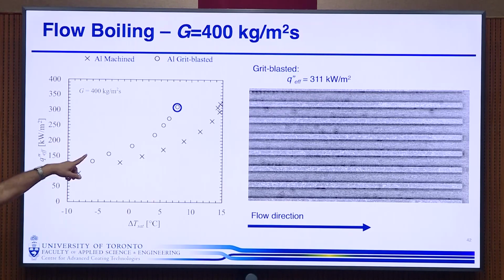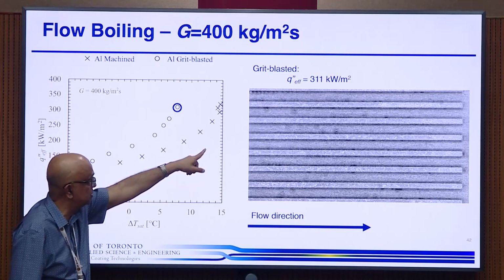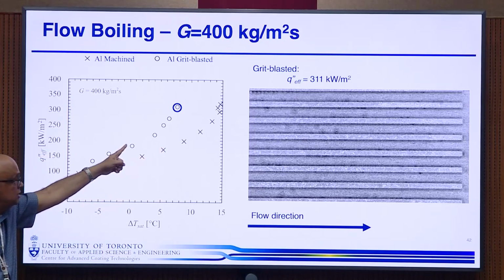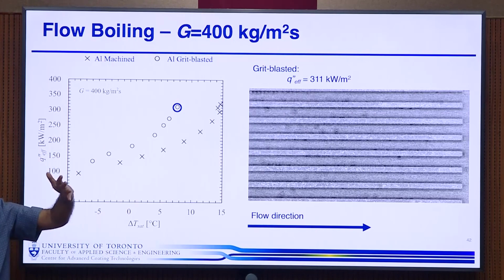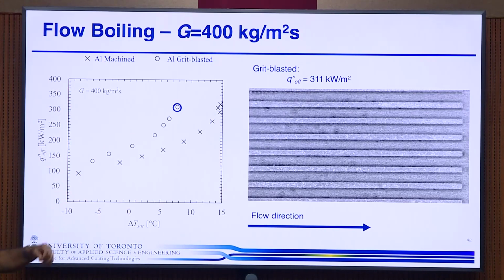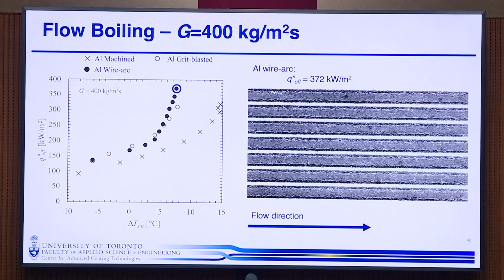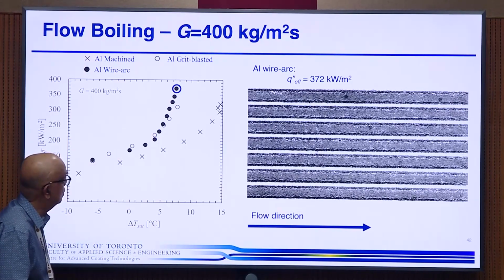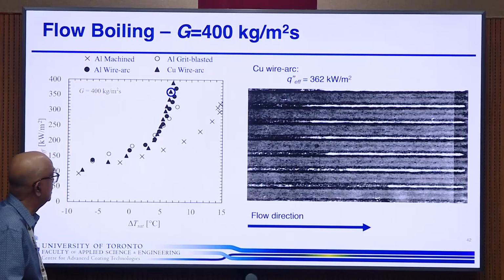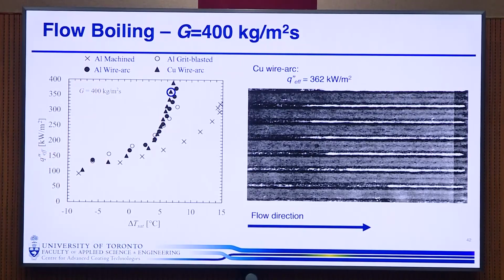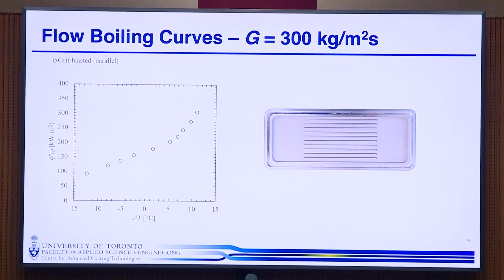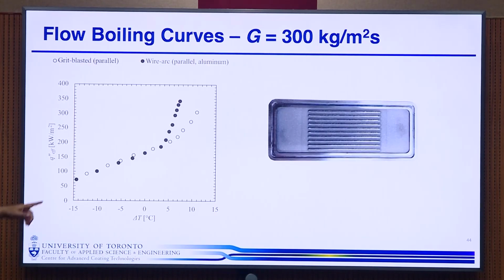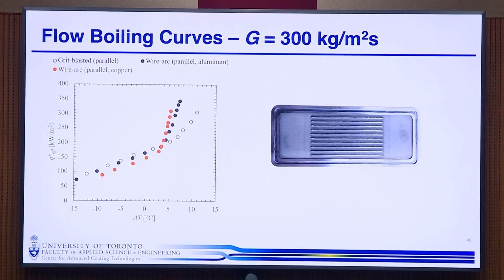Okay, so this now is the grit blasted one. And in this case, the bubbles are more visible. You can see them. And you can see how increasing the roughness increases the heat transfer quite significantly. And so you get much more nucleate boiling. This one is the aluminum wire arc. And so we've increased that even more. And this finally is the copper wire arc. So they're all sort of lying around over that. So our surfaces offer much higher heat transfer. This is at 300 kg per meter square second. And again, you can see our wire arc. This is the wire arc copper.